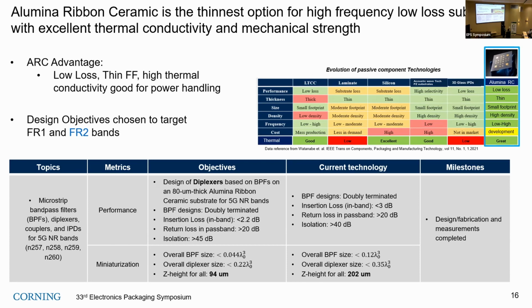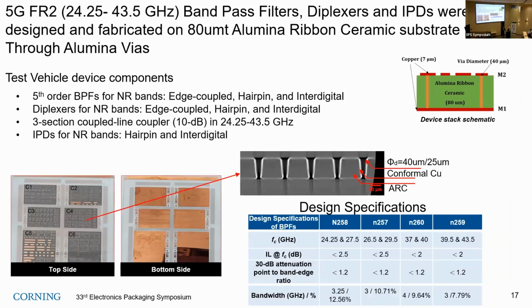We fabricated this in collaboration with Georgia Tech, their PRC center, and we designed 4 different test structures, especially the 5th order bandpass filter for the NR FR2 bands, with 3 different topologies: edge couple, hairpin, and interdigital structures. We also designed diplexers in the same band, and IPDs, which are couplers in combination with the diplexers. And we saw how the performance is.